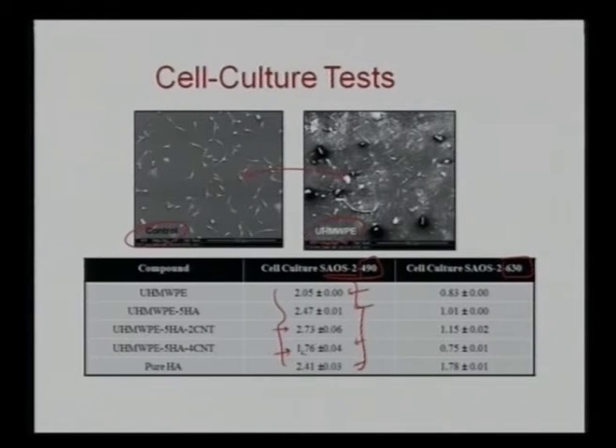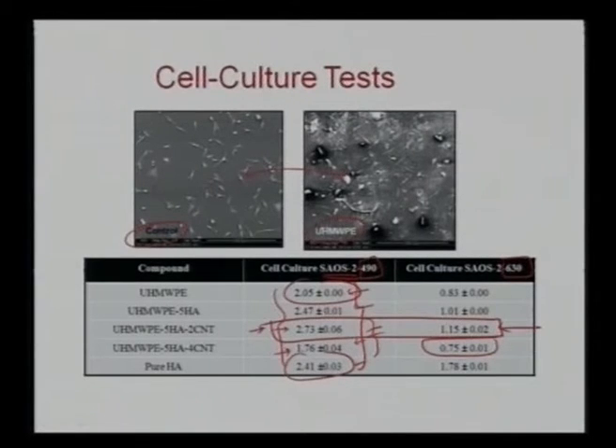If I had a pure HAP or a polyethylene, I am seeing my CNT is approximately the same. Though I can see a certain decrease in the cytocompatibility, but not to a very large extent. But my 2 weight % CNT is showing much more superior properties as compared to the 4 weight % CNT. So overall, we can say that we can achieve some marginal improvement in the mechanical properties without deteriorating the cytocompatibility of this particular composite.